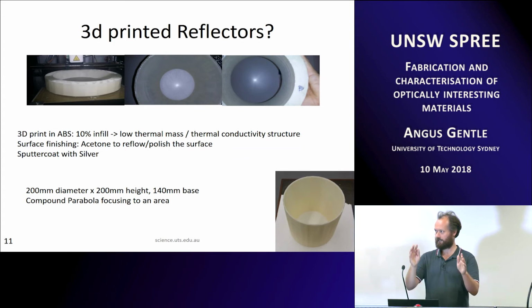And we went, we can design these, so you can use a CAD program, design your perfect parabolic reflector, which reflects down to a surface, and then 3D print it. So printing it in ABS, 10% infill, so it doesn't conduct very well. And then when you 3D print, you get this sort of rough surface. You can reflow with acetone. So put some acetone on it, you can get a nice polished surface on it.